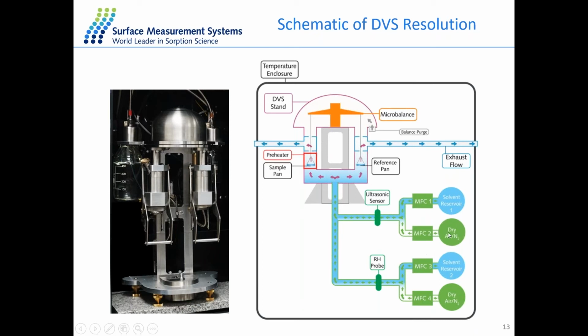The carrier gas for the system could be nitrogen or dry air, and there are different mass flow controllers to control the flow of the carrier gas and the saturated vapor in ratio to reach a certain level of relative humidity or partial pressure. This mixture will be detected by the sensors here, the Rotronic probe for the water and our speed of sound sensor for the organic vapors. And we will make sure the actual generation of the vapor matches the target concentration. This mixture will flow to both the sample chamber and the reference chamber at a constant rate.